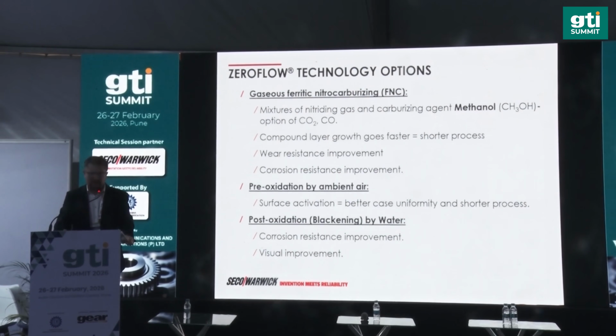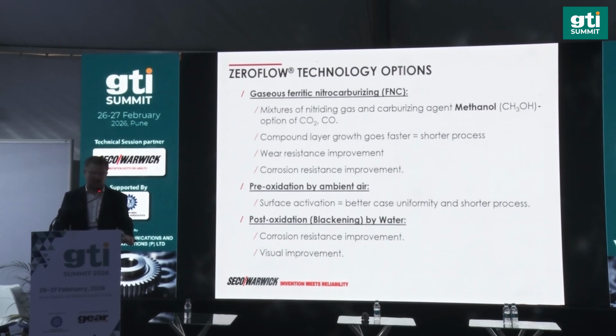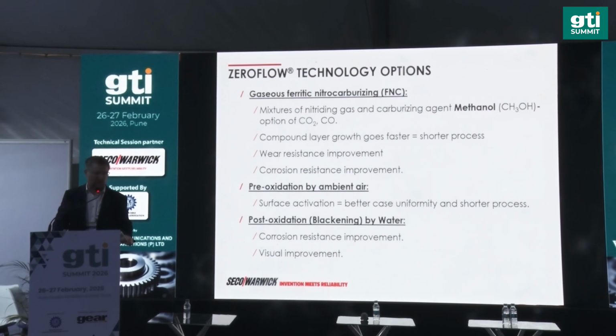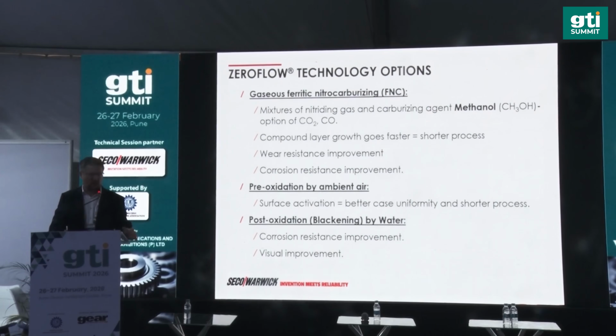We recommend methanol because it's a very cheap solution and gives much better results in terms of porosity of the nitriding layer. It could be compared with CO, but it's much easier to use in the industrial environment compared to CO, which could be toxic.